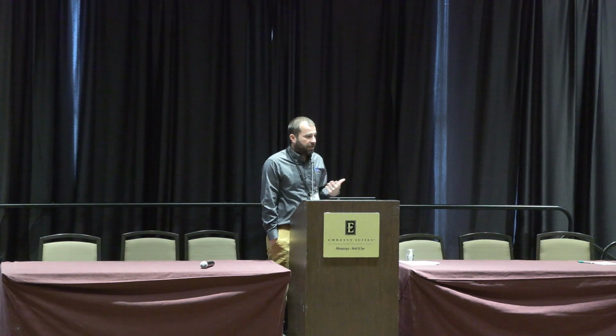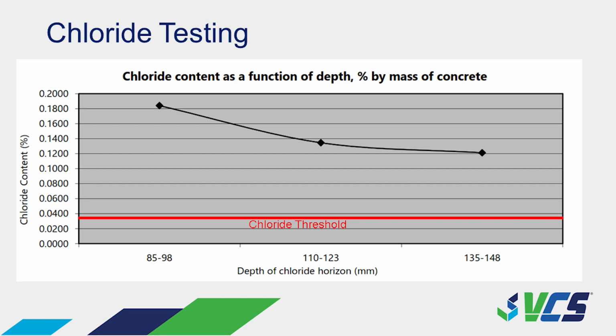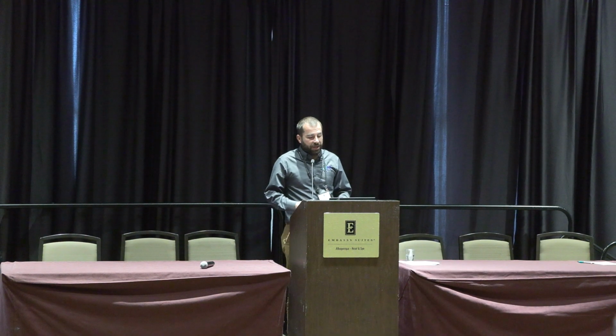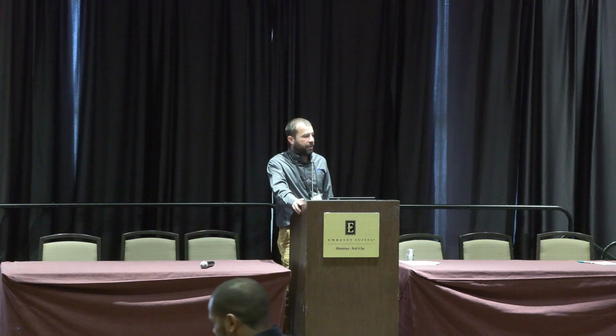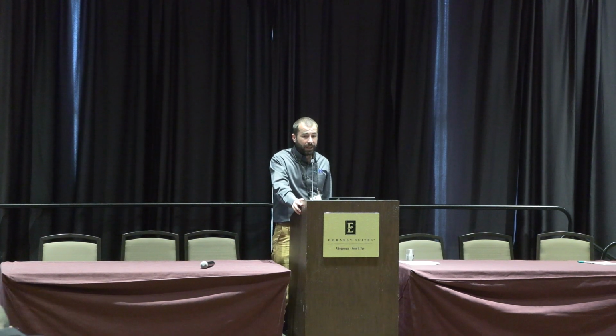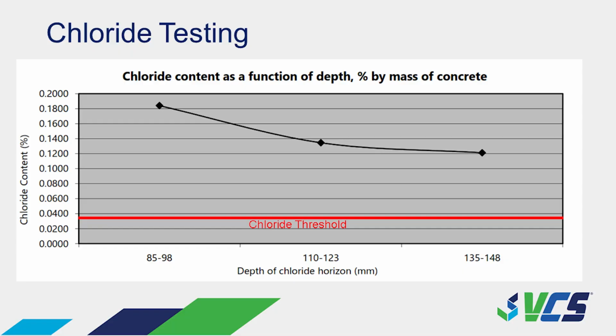It is a very exposed environment. There's a lot of de-icing application. Here you can see an example of one chloride profile from the deck. The horizontal red line marks the chloride content above which corrosion initiates. If we're above that chloride concentration, the risk for corrosion is high. Here's one example where the chloride concentration with depth in that deck is quite high, and it varies throughout. There are some areas that are relatively low, and some areas that are really high like this.